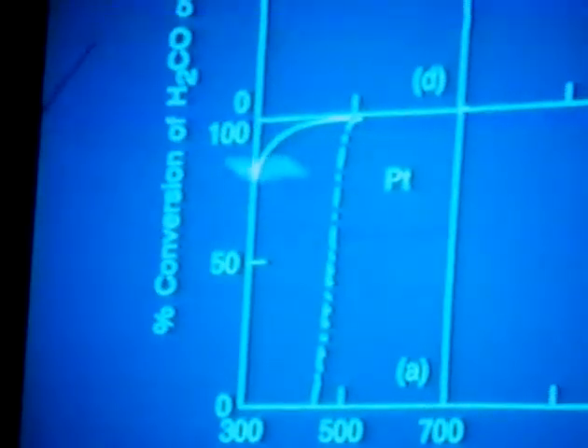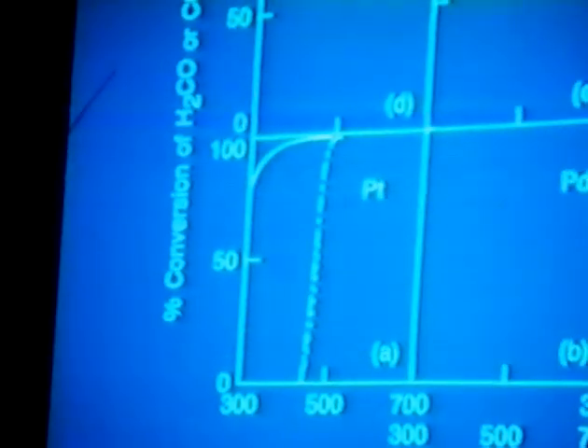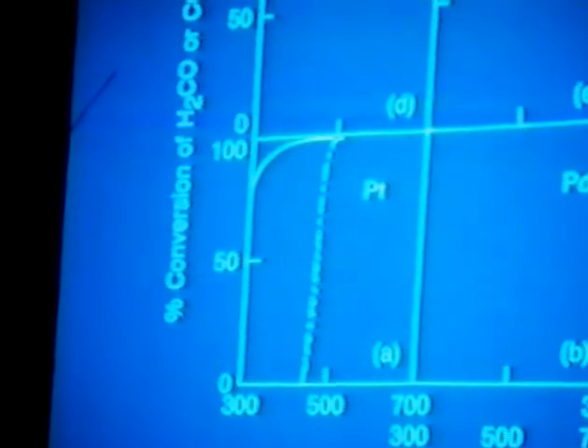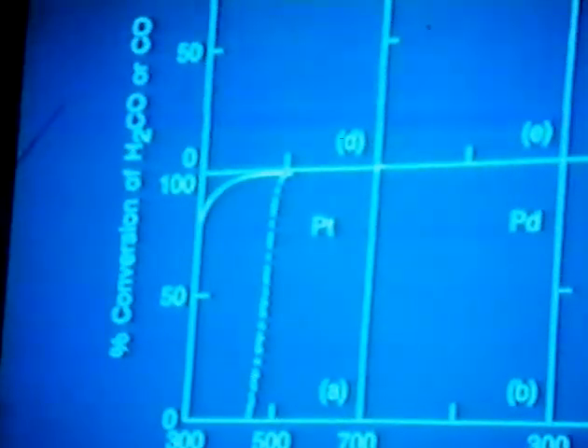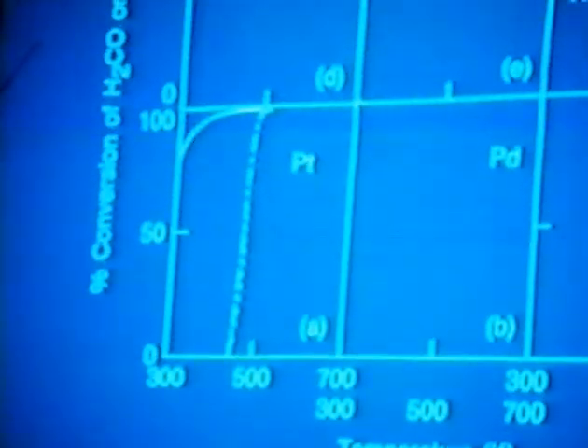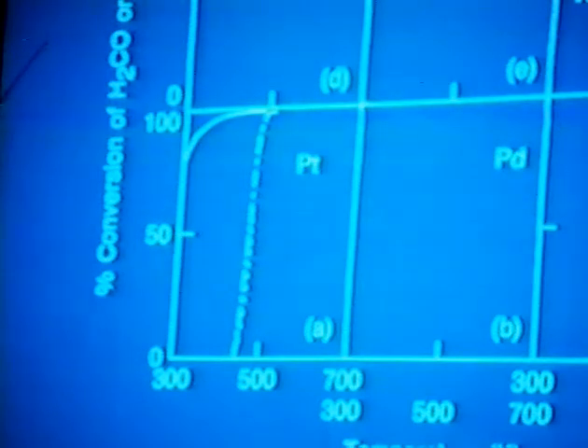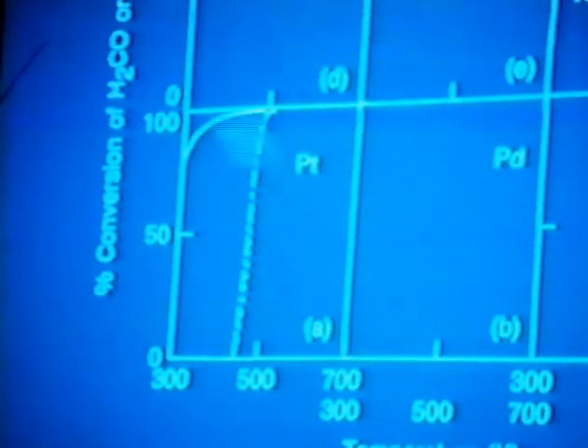Now, for the case of the platinum catalyst, what you can see here is that for formaldehyde oxidation by itself, platinum is extraordinarily active. Even at room temperature, we got significant conversion, and by 400 Kelvin, we were essentially completely converting the formaldehyde. However, when we looked at formaldehyde oxidation in the presence of carbon monoxide, we found that the results were quite a bit different. In fact, we got complete inhibition, suppression of the formaldehyde oxidation until we reached temperature